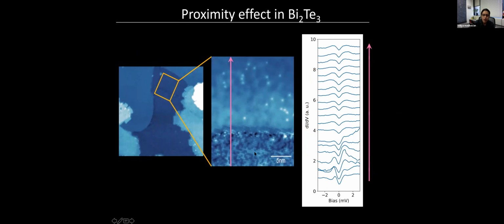You can see this proximity effect. The proximity effect is really interesting. This is bismuth telluride, and what you see is a shallow gap on bismuth telluride. Remember, this is a lateral proximity effect. So one imagines that only the surface state is getting proximitized. The gap magnitude is also pretty small compared to the gap magnitude on FeSeTe.